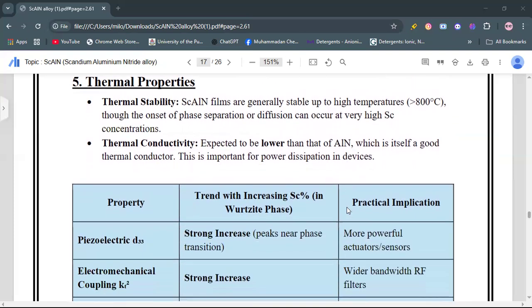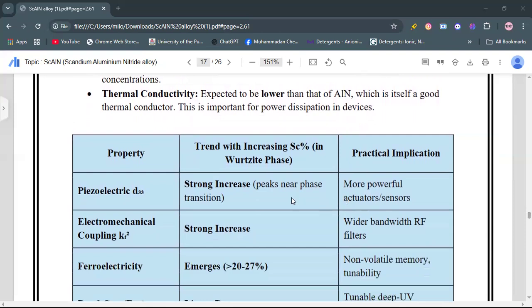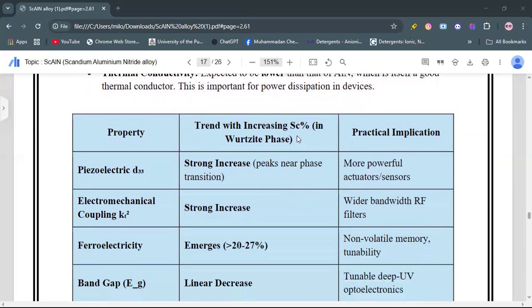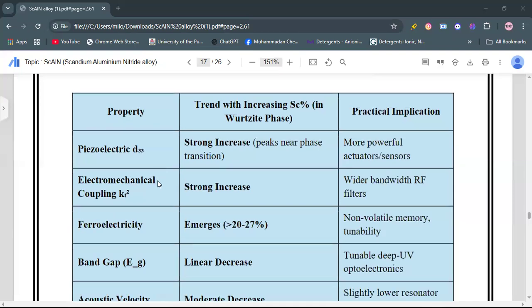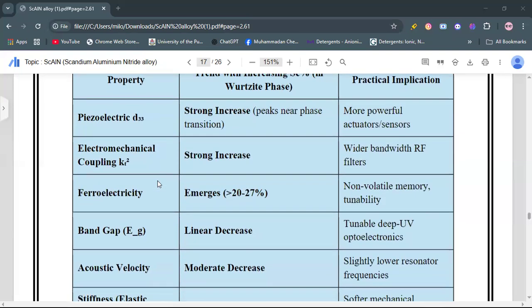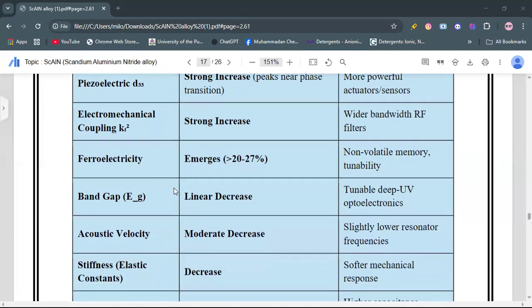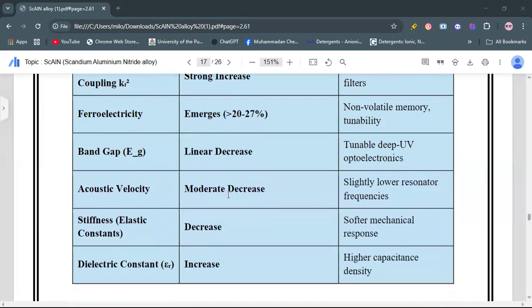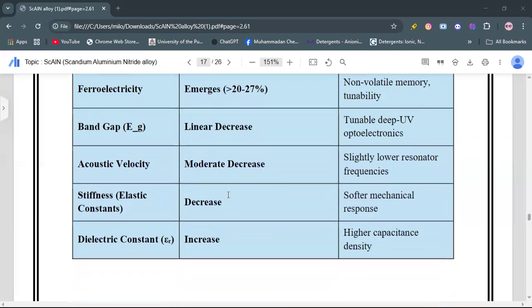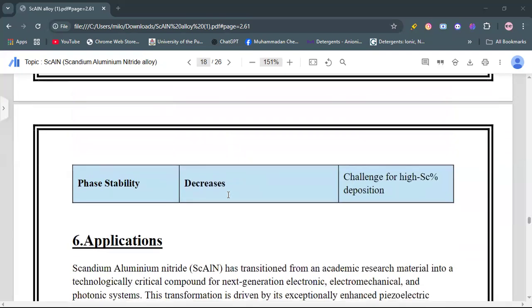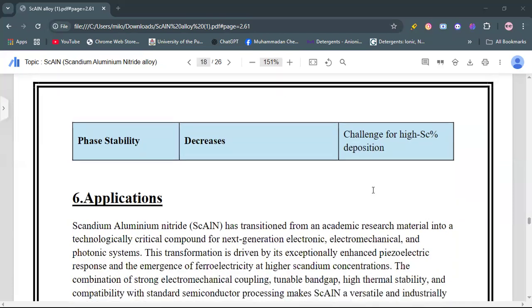So this is the table that represents various properties of scandium aluminum nitride. When scandium is introduced into the aluminum nitride, piezoelectricity increases, electromechanical coupling increases, and ferroelectricity increases, but at specific concentrations, band gap decreases, acoustic velocity moderately decreases, stiffness decreases, dielectric constant increases, and phase stability decreases, which is a challenge for high scandium deposition.